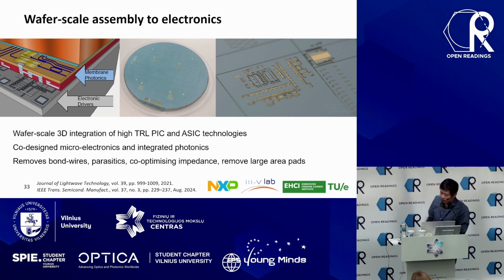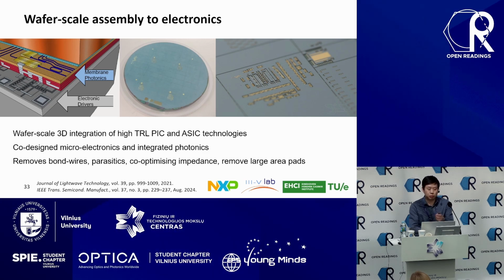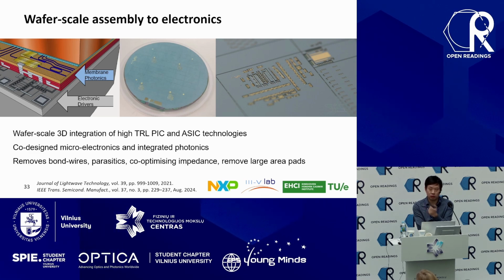The major benefit, as I indicated here, is to remove the bond wires or bumps which people typically use for chip assembly. When you need to assemble an individual photonic chip and electronic chip, you need these bond wires, which are centimeters or millimeters long. And if you talk to experts, they say they have super high parasitics, which will become the bottleneck of your entire system. So in this case, since we do 3D integration, we are bringing the photonics and electronics really close, down to several micrometers. So we are shrinking the distance of the interconnect by several orders of magnitude. So in principle, we can make much faster interconnects between the two systems.